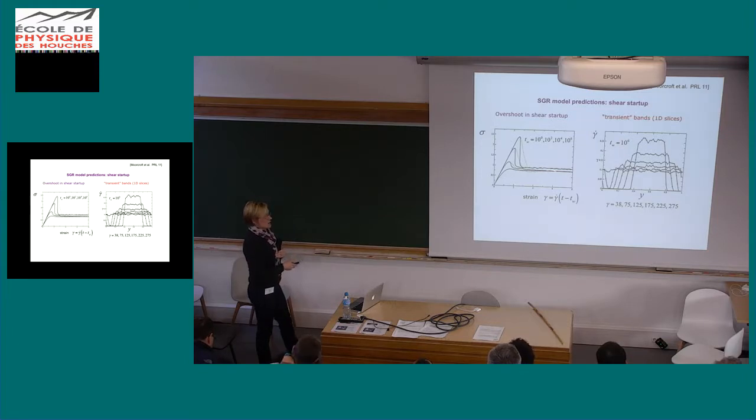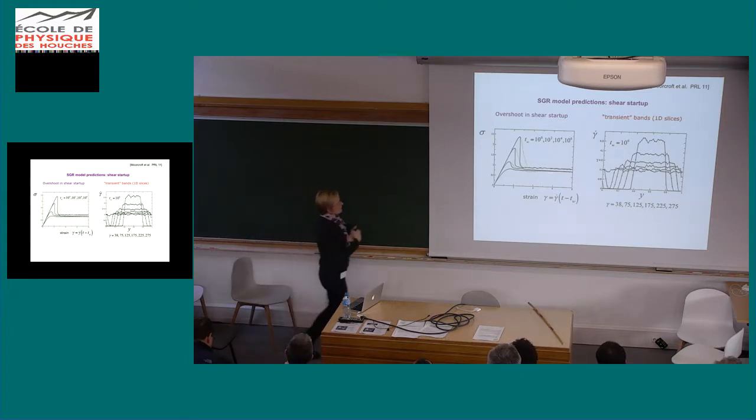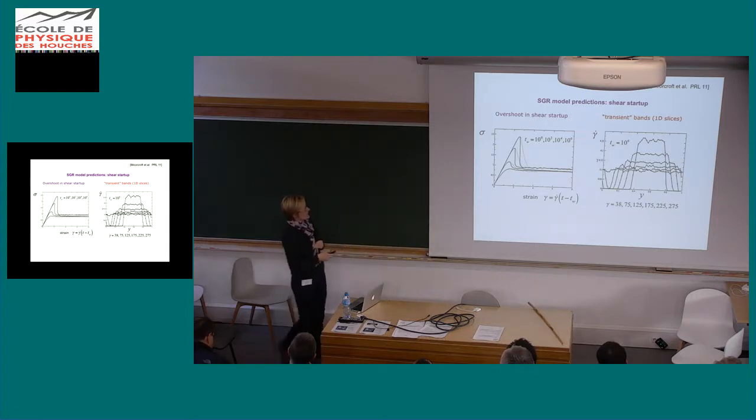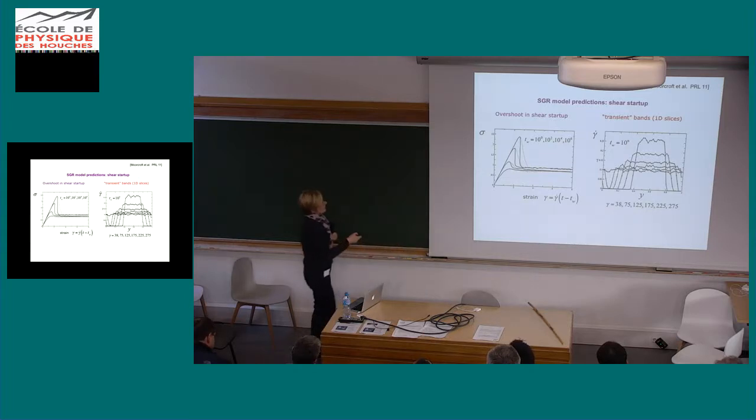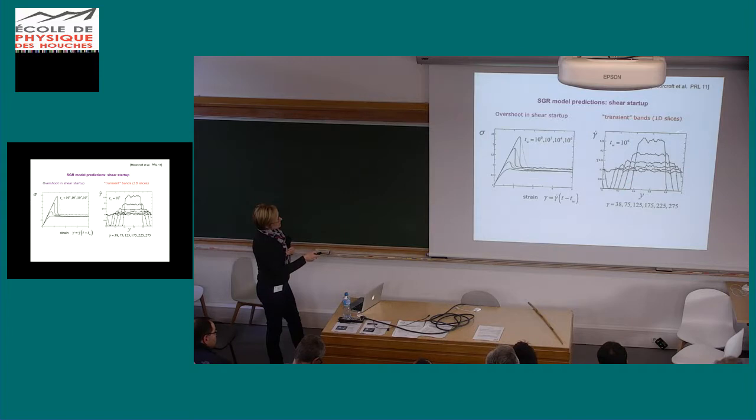Now this is computed within the homogeneous model. We then run the model in the form that allows for the formation of heterogeneous shear banded states, and that's the solid curves. And you see that these align with the homogeneous model initially. That's because the flow remains homogeneous, even in the model that could allow heterogeneity. But as soon as you go near this overshoot, there's a very precipitous stress drop that eventually, not actually on this scale of strains, reaches the steady state flow curve value. And concomitantly with that, you see the formation of shear bands. So this is shear rate as a function of position across the gap at several strains that are actually way off the scale here.